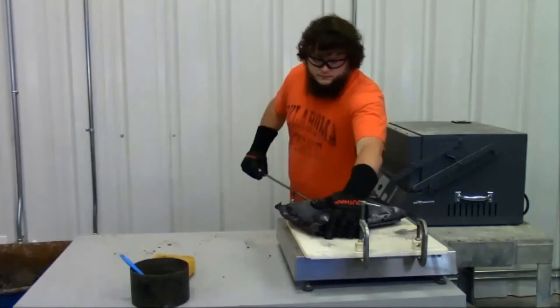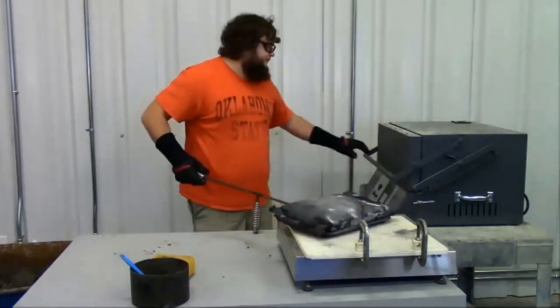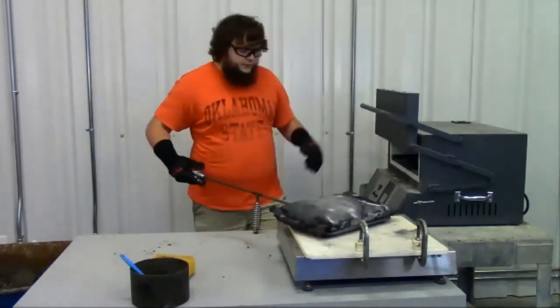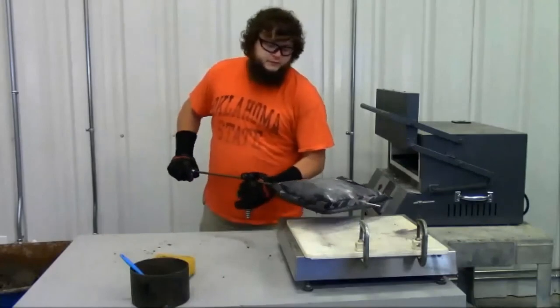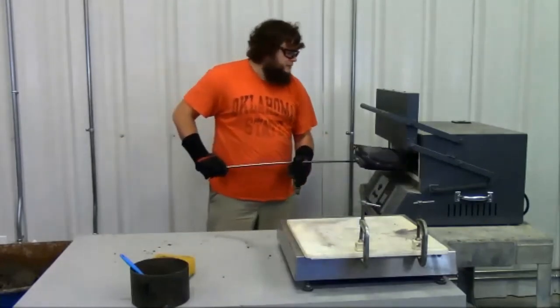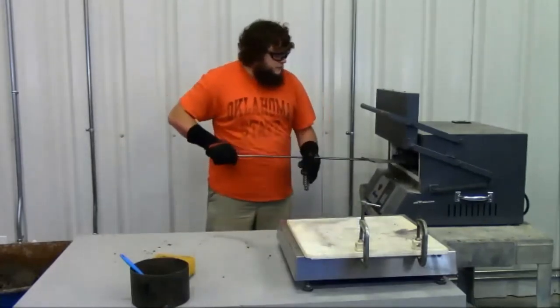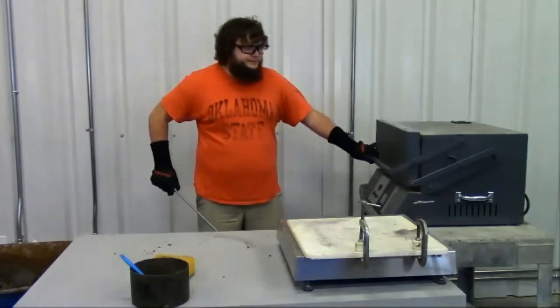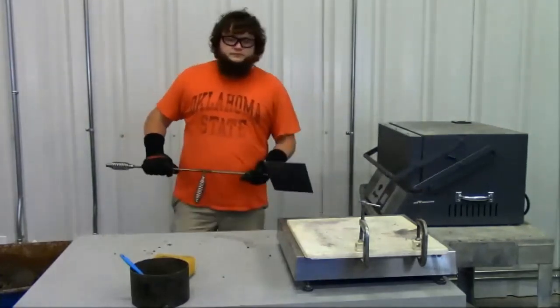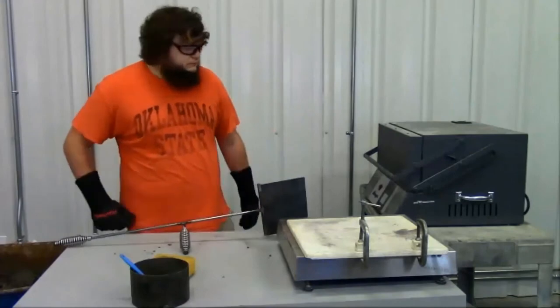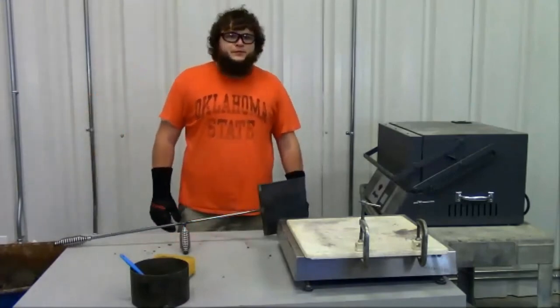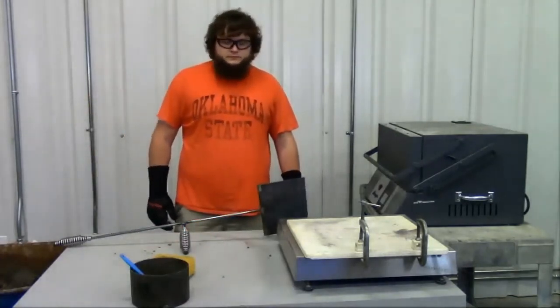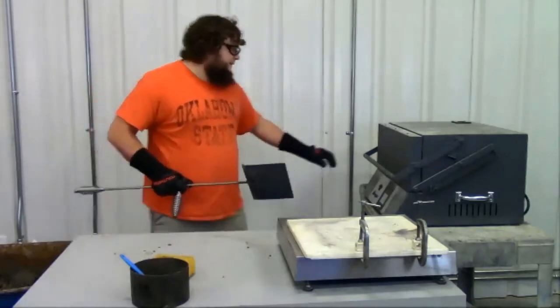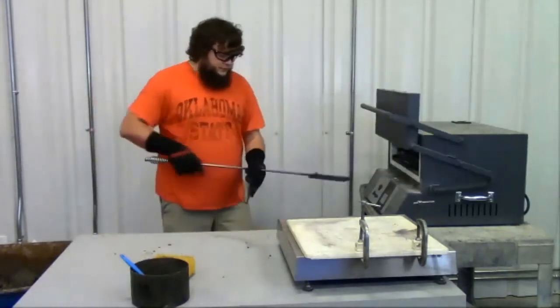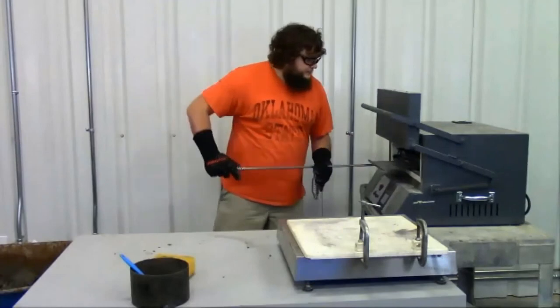Once recorded, use the steel spatula and the heat-resistant gloves to put the pan, wire mesh bag, and sample into the preheated kiln. Leave the sample in the kiln to dry for 15 minutes. After 15 minutes has elapsed,